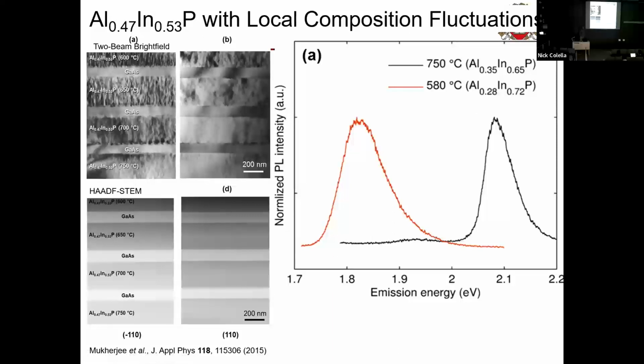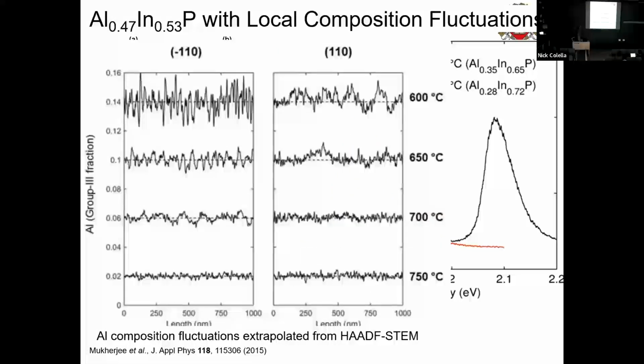The other problem was, you go and look at it in a TEM, which would be the usual way you would look at this sort of material and see if there was some structural problem, like it wasn't crystalline or whatever. And okay, there's some odd, rough, mottled texture in there. But if you kick in the kind of TEM you would normally use to see big composition differences, you don't really see anything comparable to the very large difference in composition that the light emitted by this stuff would suggest. Why not? And let's talk about that.